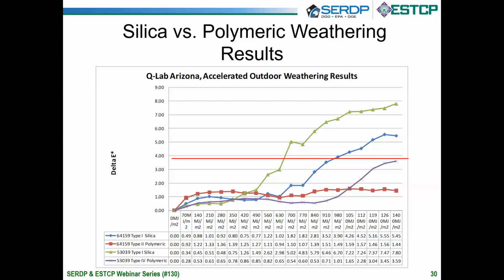And again, this was all done through the initial SERDP effort. And this was a gap that when Fred was working and developing these materials, the go-to was using silicas and highly flattening. And even to this day now, we're looking for alternative flattening agents that we could use less of and have a more resin-rich system.